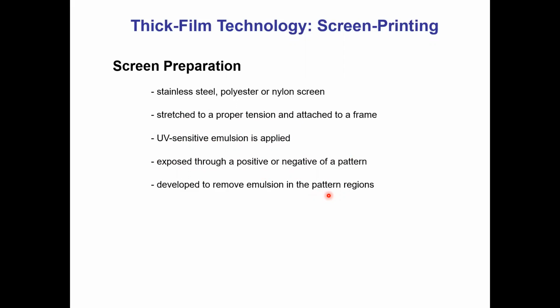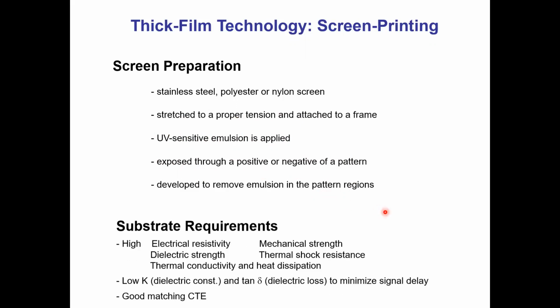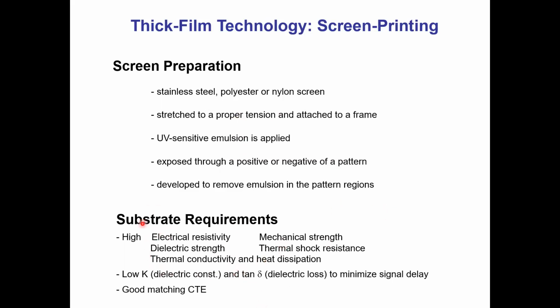to print your device. In terms of substrate requirement, there are some generic requirements, but in general, you need good thermal coefficient matching between the film and the substrate to avoid microcracking, good mechanical strength, thermal shock resistance, good electrical resistivity. The rule of thumb is that since you're measuring a coating which is sitting on top of the substrate and the electrode is in between the substrate and the sensor film, your electrical resistivity of the substrate has to be 3 orders of magnitude higher than the film.